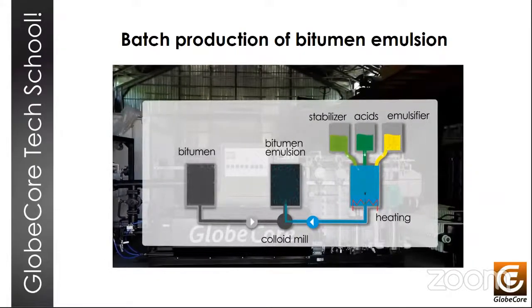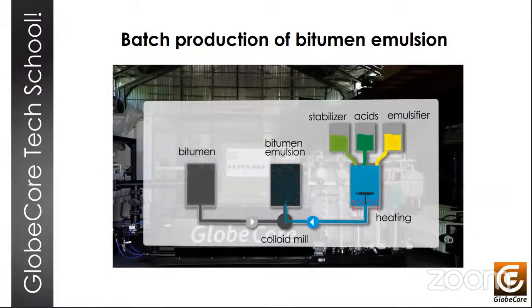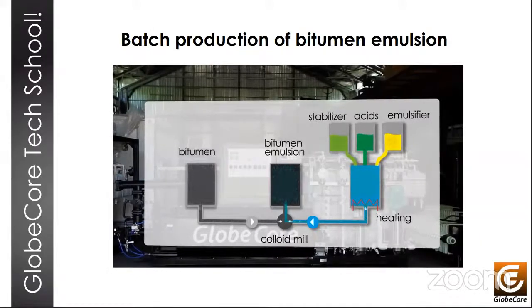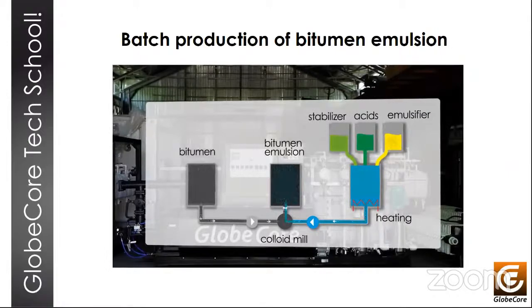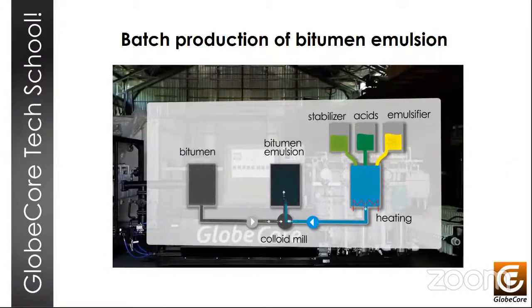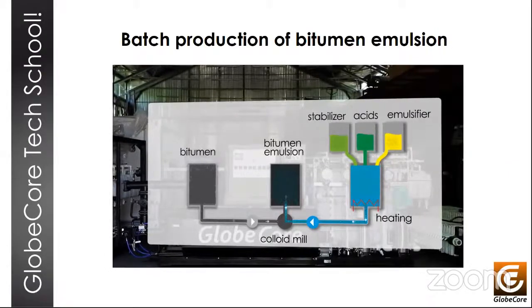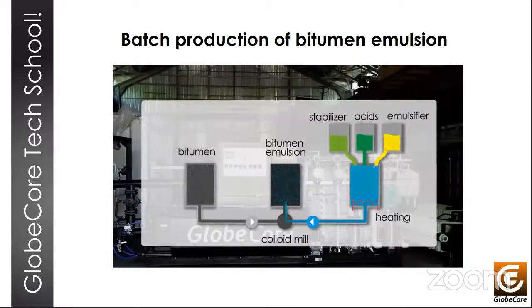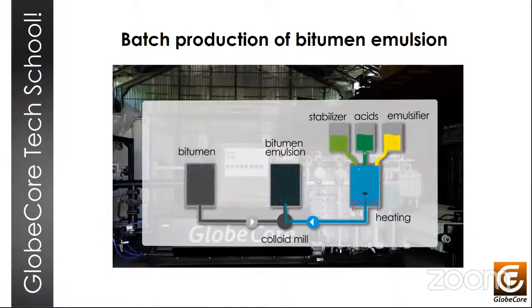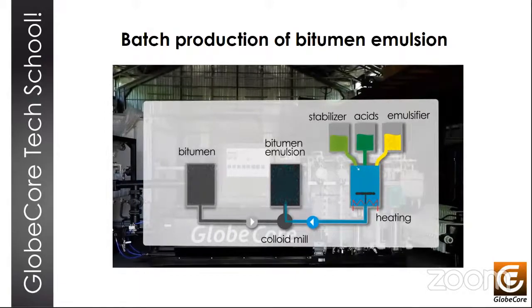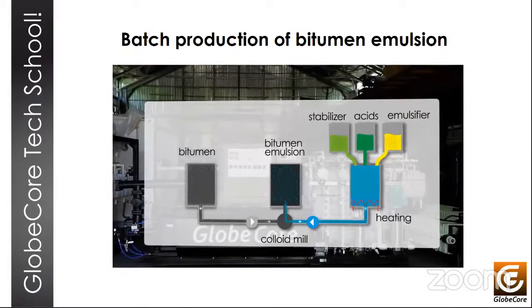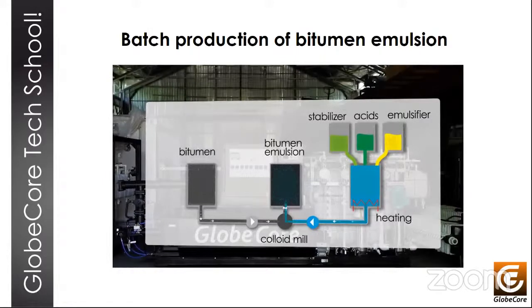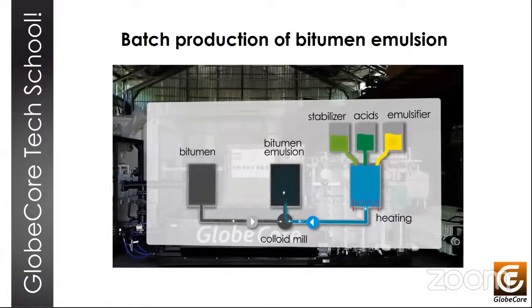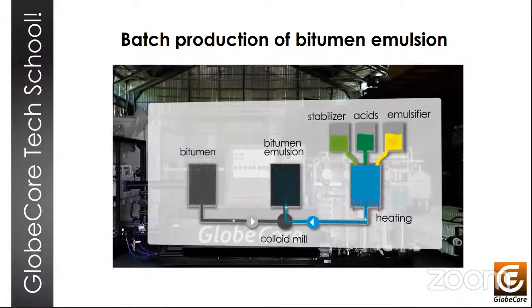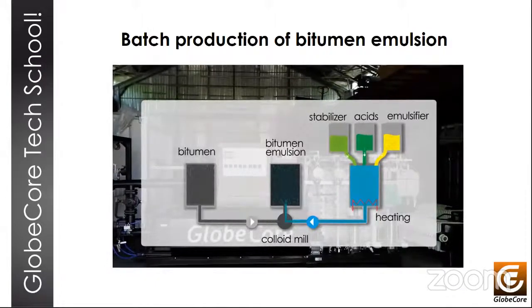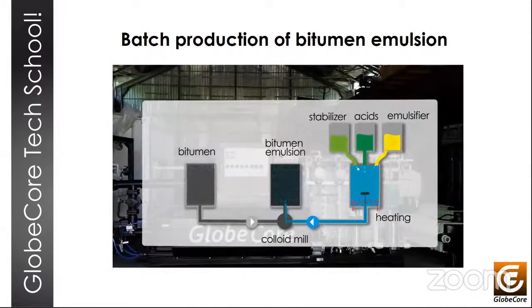For the preparation of bitumen emulsion, we can have batch or continuous production plants. The batch production process consists of at least two stages. The first stage is the preparation of the so-called water phase, or soap phase as it's sometimes called, and the actual production of the emulsion is the second stage. The water phase is prepared in a tank into which we supply heated water, emulsifier, acid or alkali, and any other additives necessary to the product formula. The resulting solution is then mixed.